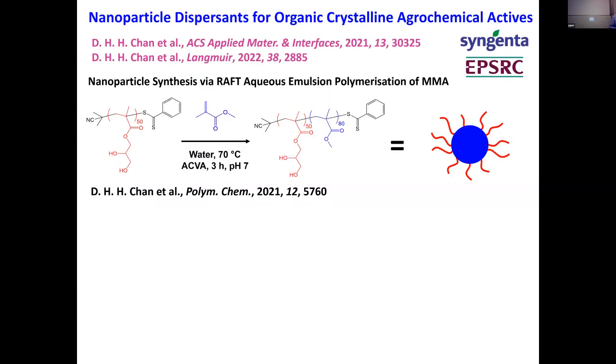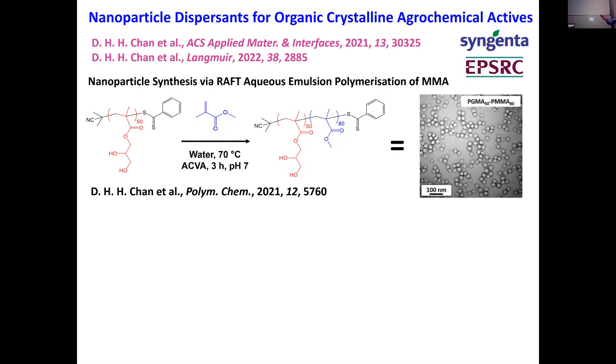So something else we've done with RAFT aqueous emulsion polymerization, using it to target very small particles, is a project which was part sponsored by Syngenta. It's a $16 billion a year agrochemical company based in the UK and Switzerland and owned by a Chinese company. So again, we use polyglycerol monomethacrylate as the stabiliser block. In this case, we use methyl methacrylate, the cheapest methacrylic monomer available, and we make sterically stabilised spheres. And again, that's not a big deal. Very, very straightforward synthesis.